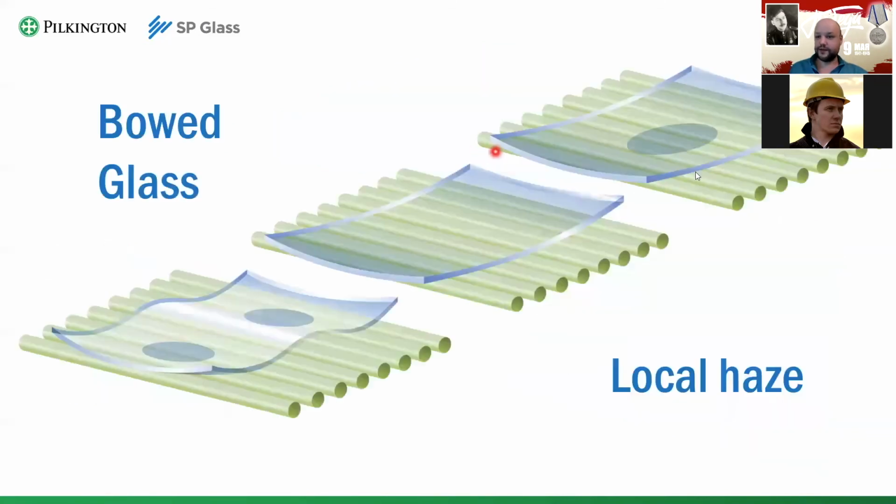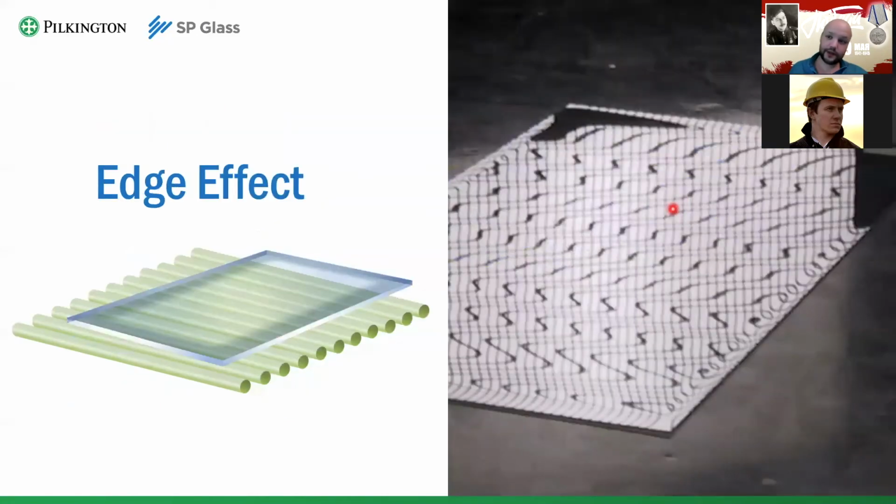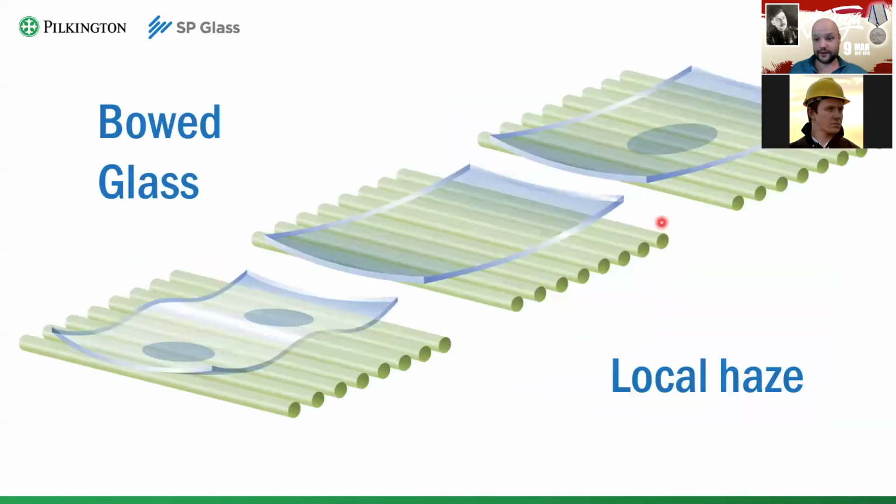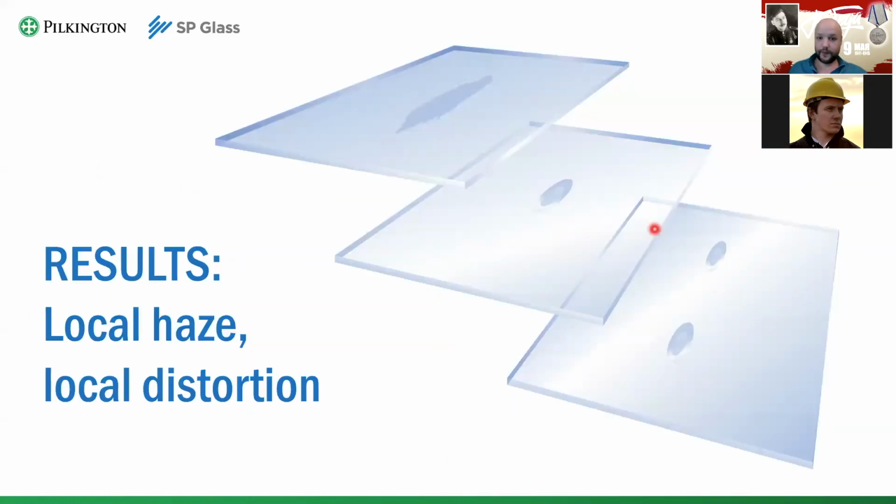If your glass moves too much on its belly, the central part has a lot of friction with the rollers. And if it has a lot of friction with the rollers, you will have a white haze on the final product. Like this. It looks whitish, like powder, a little bit powdered, from too much friction. White haze in the central part. Sometimes it will not be straight, it will be bent to some degree. But this is also a sign that your glass was not tempered properly enough.